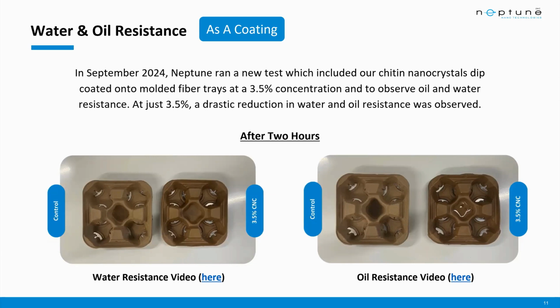So in September last year, a little while back, we built some early coating prototypes and we put our theories to the test. So what we did was quite simple. We diluted our chitin nanocrystal concentrate, which, if you recall, is in a water-based slurry, with further water to the point that it has good flow characteristics to be used as a coating application. And in this case, it was about 3.5% by weight. And then we simply dip coated a few of the molded fiber trays that you can easily buy at your local coffee shop. We dip coated them and simply allowed them to dry. It does not require a specialized curing process at all. It's quite simply drying and evaporation. And then we proceeded to test their water and oil resistance.